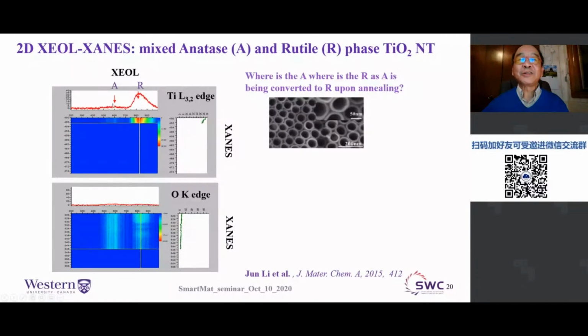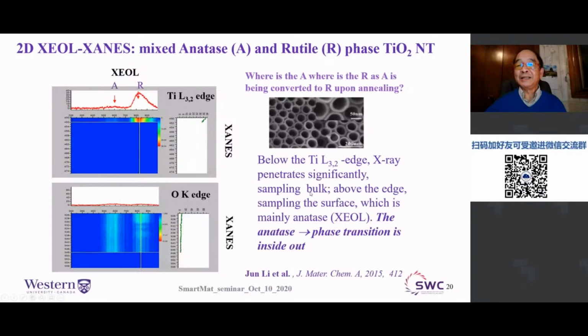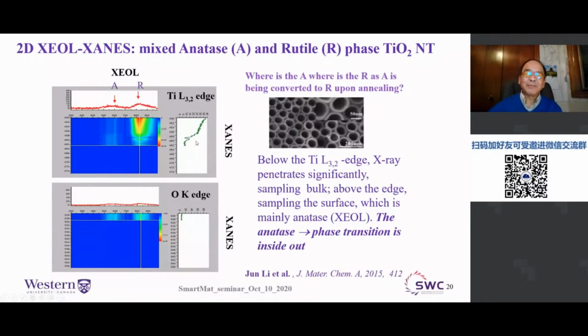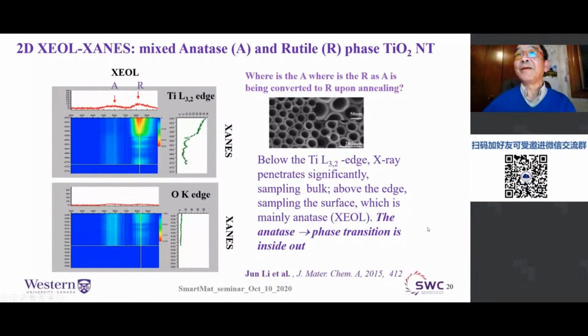And you can see there's a drastic change in the branching ratio, which is due to a combination of where you're exciting and the penetrating depth of the soft X-ray. So I'm not going to go into that in detail. So the outcome of analyzing the data, we come to the conclusion that the anatase to rutile phase transition is inside out. It starts from inside and then goes out.